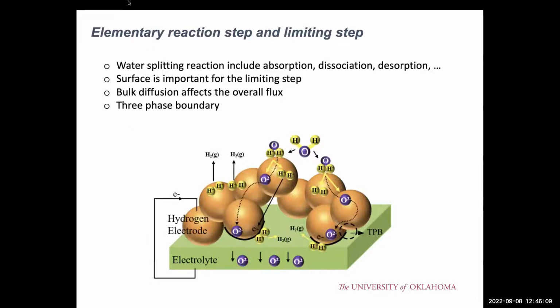So for the catalyst, it's very important to control this adsorption, dissociation, and desorption. So we want the water to be easily adsorbed on the surface, but we don't want that adsorption to be very strong, because after the dissociation, if it's too strong and the species cannot desorb very easily, it can further limit the reaction. So we should find a good balance between adsorption and desorption. And so the surface property is also very important. So we have a term called the surface exchange coefficient to describe how frequent this kind of chemical reaction is. Sometimes the surface is an important aspect for the limiting step, which can limit the overall water splitting rate.